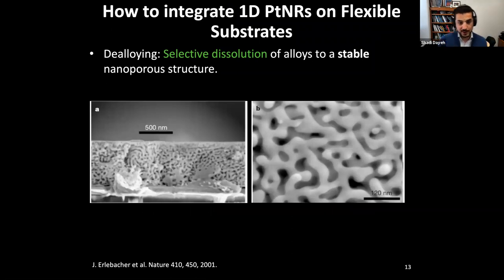So we want to use platinum and we want to benefit from the large surface area of the platinum. If we want to synthesize one-dimensional or three-dimensional structures of platinum using conventional techniques, we need high temperatures. But these electrodes need to be made on a thin, flexible, polymer-like substrate so that they can adhere to the surface of the brain. Therefore we need to come up with a way that is compatible with a low temperature process. We found that manufacturing way in a paper published in 2001, where they use selective dealloying. In this case, the authors co-sputtered silver and gold and selectively etched silver from the alloy. Usually silver is etched from the surface, and then to minimize the surface energy of the remaining alloy, silver diffuses to the surface and it gets continuously etched by nitric acid.